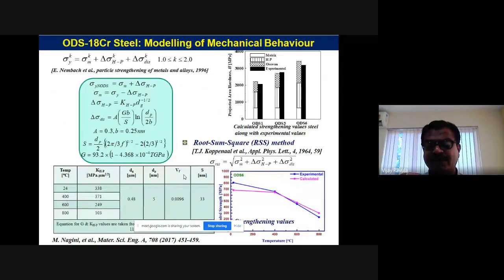And we have also done the modeling, because as I mentioned to you, it's a summation of the individual strengthening components like matrix strength, Hall-Petch strength, or the dispersion strength. But we found at room temperature that they don't follow linear summation, but they follow the root sum square method, and you could see that our experimental values and the calculated model values are matching. And these are all papers published in Materials Science and Engineering A, or Metallurgical and Materials Transactions A, or even an Acta paper. They are all published.